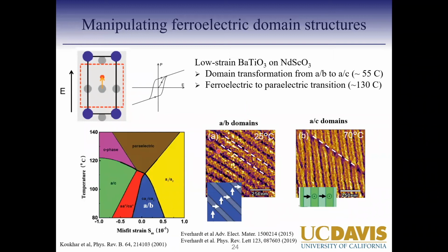So we looked at a specific strain, which was located right around this negative 0.25 value, where at room temperature we have these AB domains aligned along crystallographic A and B directions, and then as you heat it up, it transforms to AC domains, where now your domains are actually lined in plane A and the C is out of plane. So your domain orientation actually changes. You can still see at 70C, there are still some AB domains present.